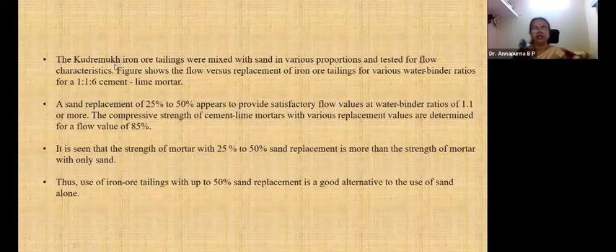For a test here, they have taken the Kudremukh iron ore tailings mixed with sand in various proportions and tested for flow characteristics. The tests were done for a 1:1:6 cement-lime mortar. Sand replacement of 25% and 50% shows a satisfactory flow, and the compressive strength of cement-lime mortars was determined for a flow value of 85%. It's seen that the strength of mortar with 25 to 50% sand replacement is more than the strength of the mortar with only sand. These iron ore tailings up to 50% sand is a good alternative to the use of sand alone.